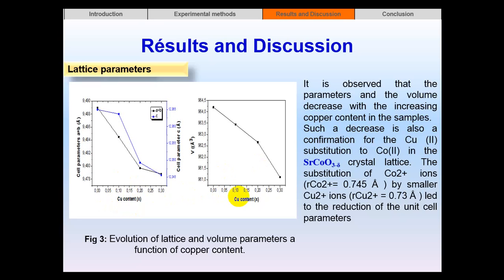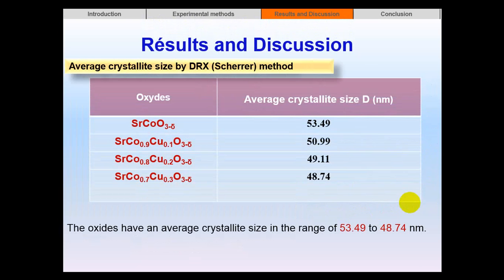The substitution of the cobalt ion with ionic radius equal to 0.745 angstrom by the smaller Cu2+ ion with ionic radius equal to 0.73 angstrom led to the reduction of the unit cell parameters. The average crystallite size calculated by the Scherrer method is summarized in this table. The oxides have an average crystallite size in the range of 53.49 and 48.74 nanometers.